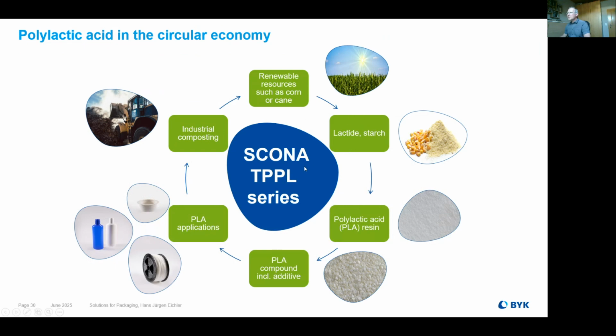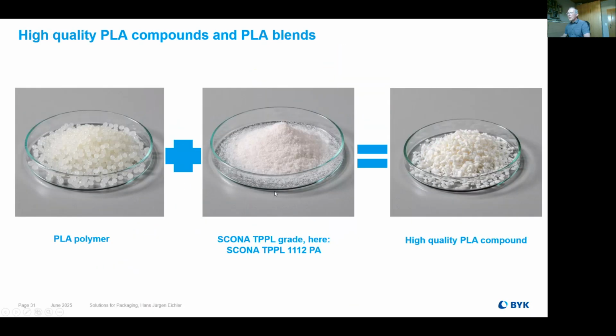And for this reason, we also have modifiers which are called the TPPL series. They are based on a PLA polymer. And you remember our toolbox of modifications, with this PLA polymer we were able to run a modification or grafting with a maleic anhydride, with a GMA, so an epoxide functionality, or an acrylic acid functionality. You see how the materials look.